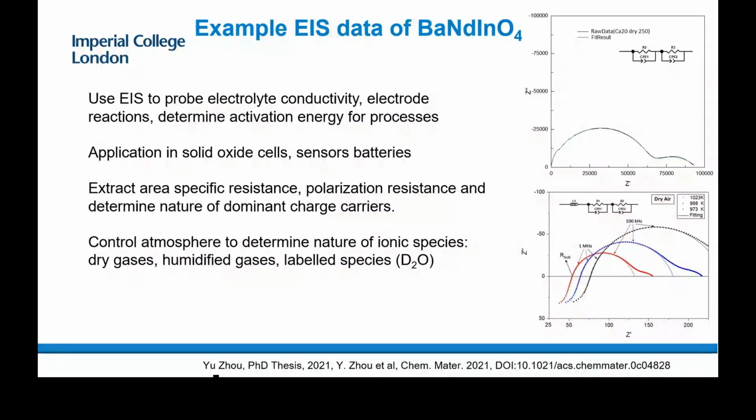Well, typically for these types of measurements, you're looking at the equilibrium. So you're typically not interested in transient species. Certainly for the pure electrolyte measurements, you would let them equilibrate, so you wouldn't measure as a function of time, effectively. You would sit at a temperature for a period of time until that sample had thermally equilibrated, and your response was unchanging, and then you would do your measurement. And then you would change temperature, let it get to temperature, equilibrate, repeat.